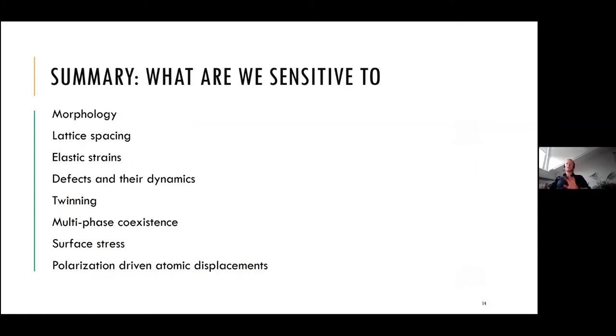So a short summary about this part, what we are actually sensitive to with the Bragg approach. We can reconstruct still the morphology, the lattice spacing, if you have some absolute reference for your measurements, elastic strains, you can image defects and also the dynamics of the defects formation inside the localized crystals. Some defects like twinning or multiphase coexistence or surface-induced stress or polarization-driven atomic displacements, all these effects basically affecting the atomic displacements inside the crystalline structure can be studied. And it's a really wide and developing field of science.